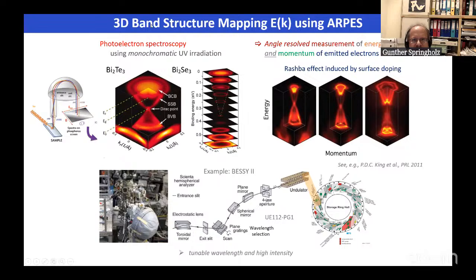The observation of the Rashba effect can be done directly using angle-resolved photoemission spectroscopy, as exemplified on this slide here. So basically, one illuminates a sample with monochromatic UV light, for instance, coming from a synchrotron source. And photons knock out the electrons inside of the material, and these photoelectrons are then analyzed using a hemispherical energy momentum spectrometer. And in this, we can obtain a two-dimensional map of the energy versus in-plane momentum, where the in-plane momentum is derived from the angular direction of the emitted electrons.